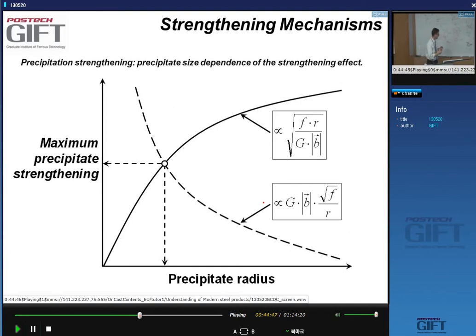So what happens? I have two dislocations on the same glide plane, one has b as a Burgers vector, the other one has minus b. They will attract each other. And so these two dislocations will annihilate and form basically a full normal lattice. And that's the reason why the dislocation can pass these particles, but they leave behind a dislocation loop that gets pinched off.